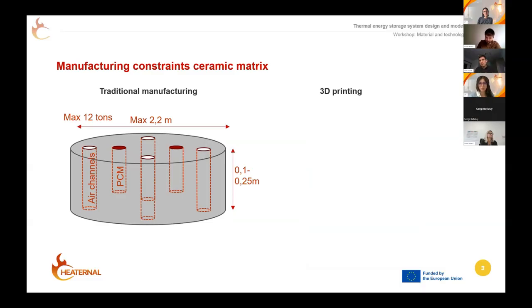There's two methods we're evaluating. The first one is traditional manufacturing. So we are casting refractory bricks, essentially large slabs in which we put air channels and PCM volumes. We have about 12 tons per brick we can do, about 2.2 meters in diameter, and a height of max a quarter meter. We can stack these bricks up to build actually a storage system. So it's a traditional manufacturing method. We know the constraints of this, and we can already design it.